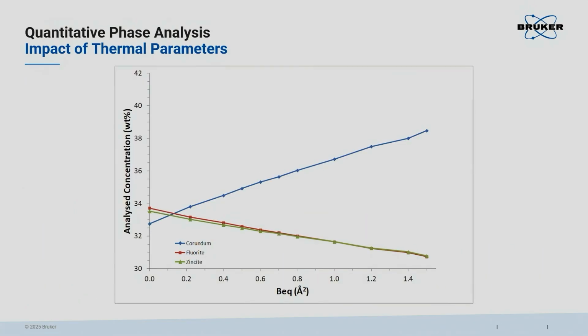This here is a plot which compares refinements, comparing the refined composition with different temperature factor values going from 0 up to 1.5. 0, as I said, many software will use default values if the temperature factors are not given. Some software is actually giving 0. I think Topas is giving 0.5, if I remember correctly. And this goes up to 1.5, the range of defaults which you can find.